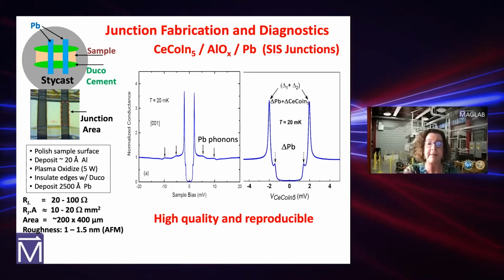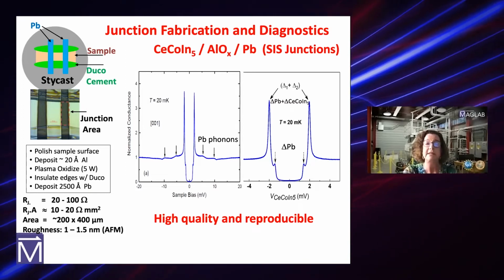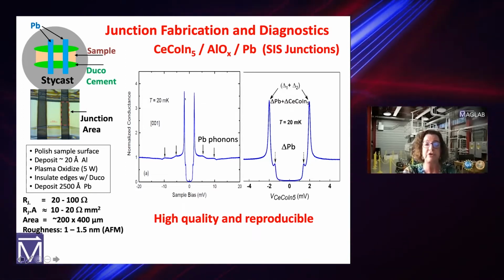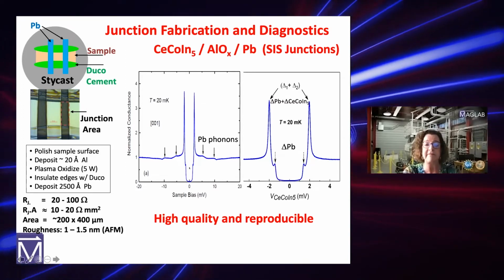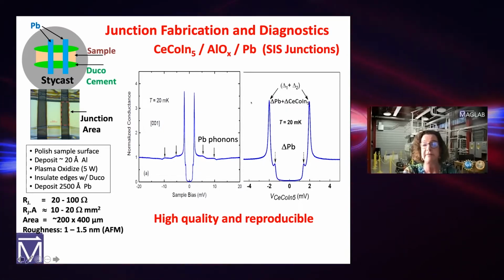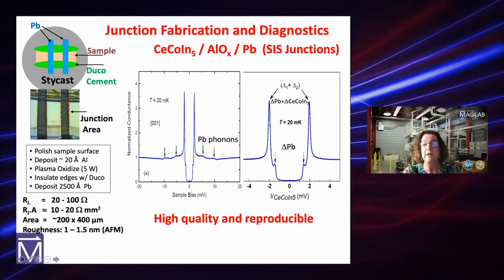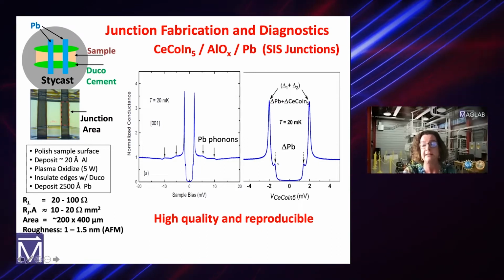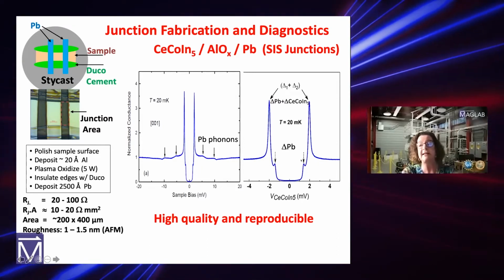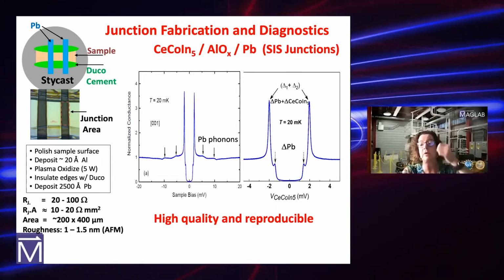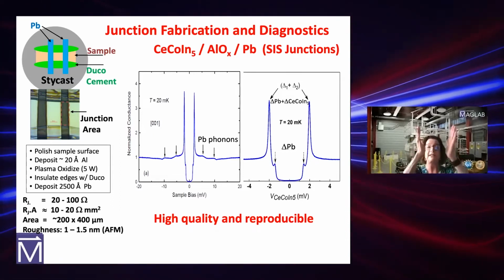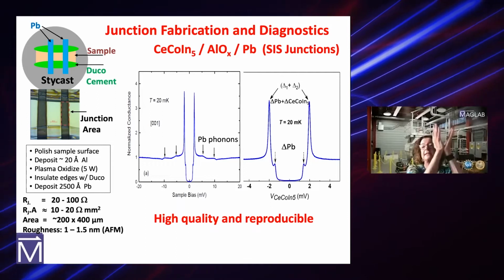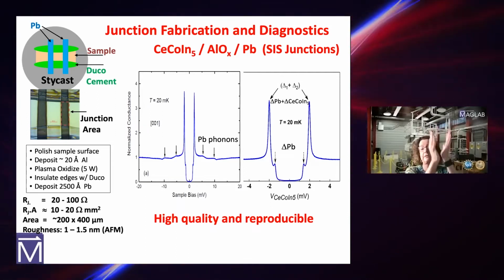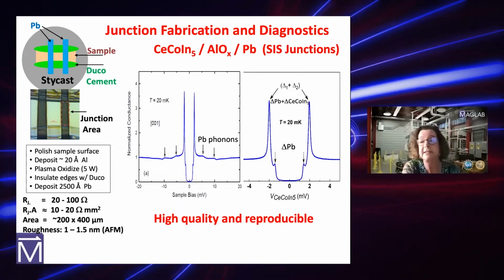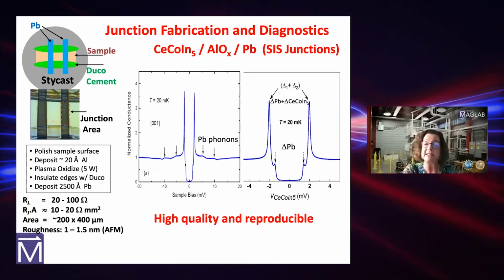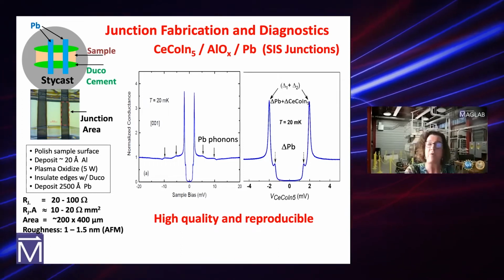This is an example of a lead insulator cerium cobalt indium-5 junction at low temperature, and we can see the lead phonons. It looks great. If we blow up the central area here, we have the delta 1 plus delta 2 and the delta lead. This is exactly what you expect. You don't see the delta 1 minus delta 2, and we'll see that there's still a lot of density of states in this dx squared minus y squared superconductor around zero bias, so you're just not going to see it. But this shows that these are very, very high quality junctions.